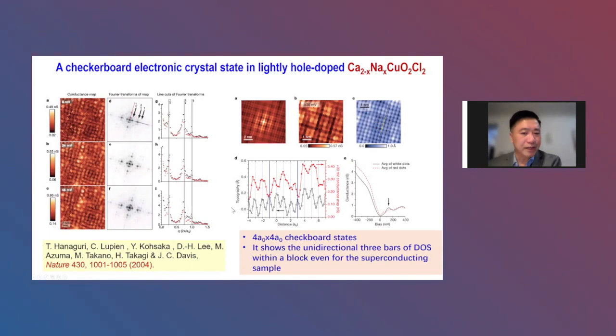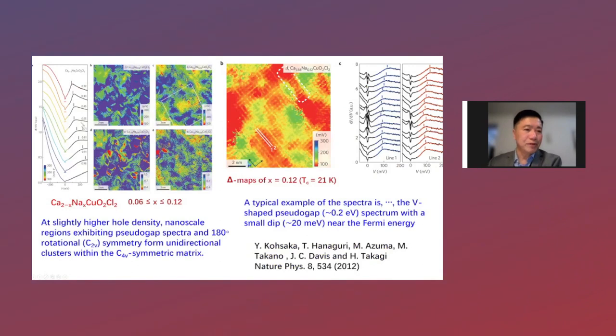So from that data, we can conclude that the 4a by 4a checkerboard is quite universal, even in the very underdoped sample, but that one is not due to quasi-particle interference. And we see this very unidirectional 3 bars of density state within the block, even for the superconducting sample. And also for other samples with a different area, you can see this big hump, pseudogap, large pseudogap, and the low energy gap. And the data looks very similar to ours, even though our sample is not superconducting, with a very similar energy.